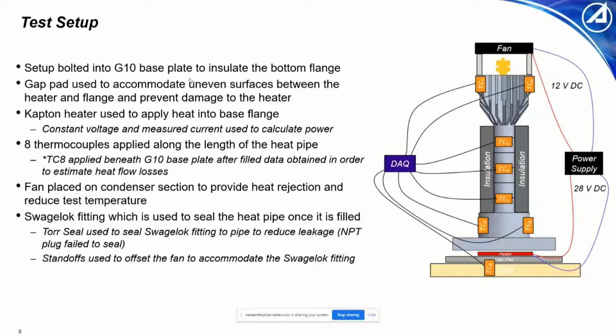We threaded the fitting into the pipe after tapping that hole at the top, then used Torr Seal to seal the fitting into the pipe. We initially started using a simple NPT plug with Teflon tape, but that failed to seal and we got leakage out of the top of the pipe, so we opted for a more permanent approach by sealing one end of the Swagelok fitting permanently into the pipe.